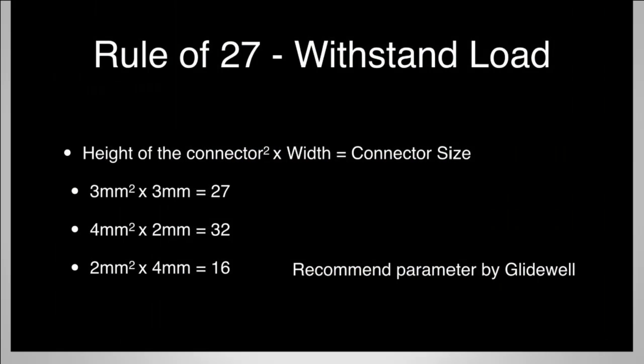Now, if we are to do a bridge, or a fixed dental prosthesis, what I would consider really looking at is the height of the connector. In zirconia, it's very important that the height of the connector is at least 3 millimeters. There's a general recommendation that's been made, and some of this data comes from Glidewell. One of the general recommendations is that if we get to 3 millimeters of connector height, that can ultimately lead to 27 cubic millimeters, and that's the magic number. So if you take the height of the connector and you square that, you get to 9. You then multiply by the width of the connector, or the buccal-lingual dimension of the connector. So height squared multiplied by width, if that total equals 27, we tend to be safe. If that number drops below 27, we have a higher risk of fracture.